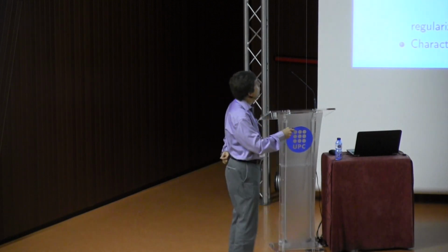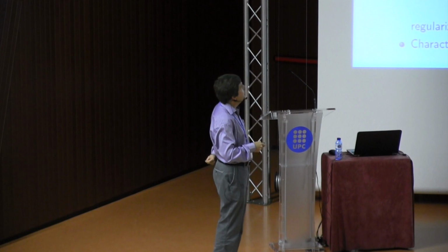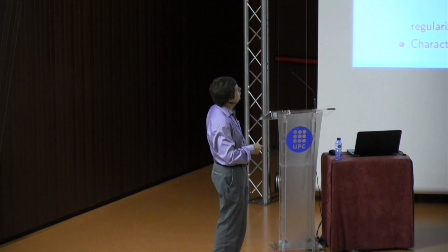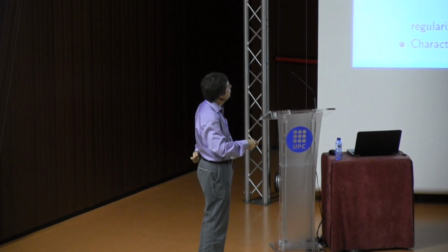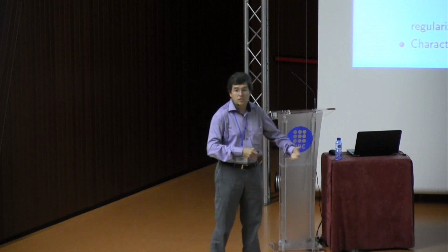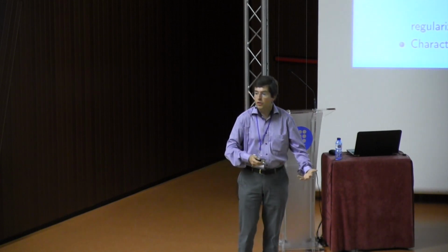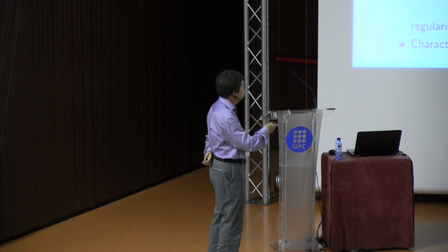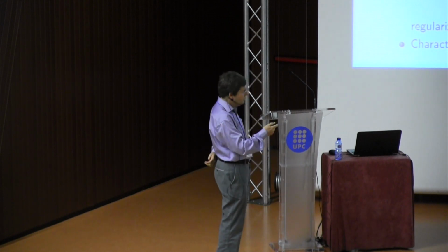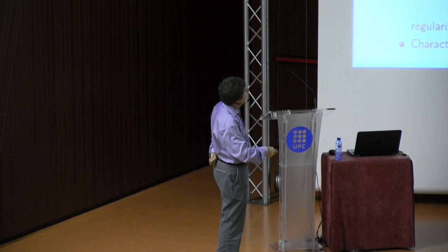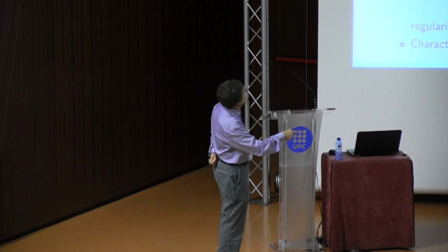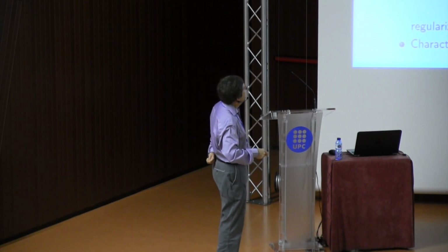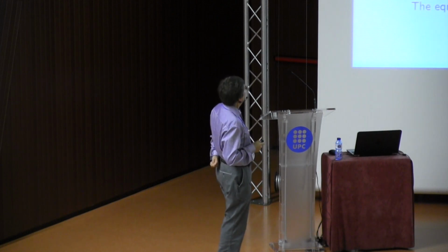If you plug the constitutive laws into this new balance equation, you end up in the isotropic case with a very simple equation, this one, which is well known. It's a sort of regularization equation, which is now derived from the constitutive functionals. You have an intrinsic length coming in by the ratio of this A parameter and this penalty term.